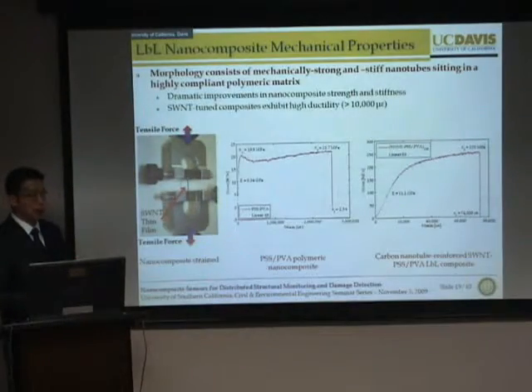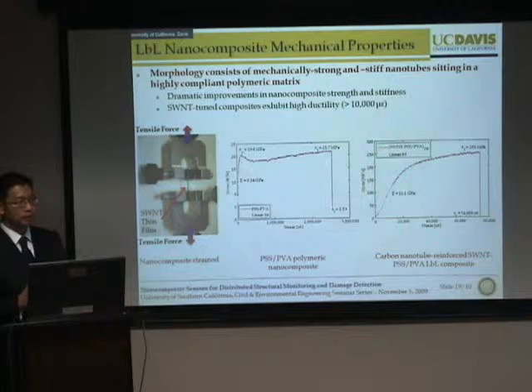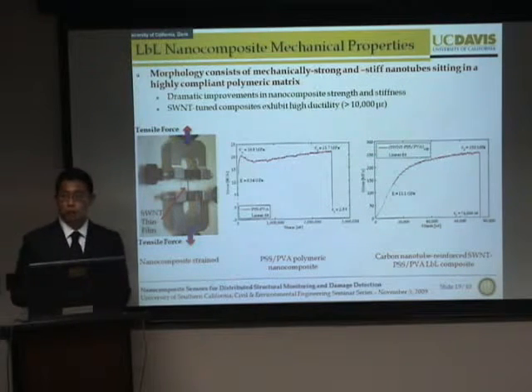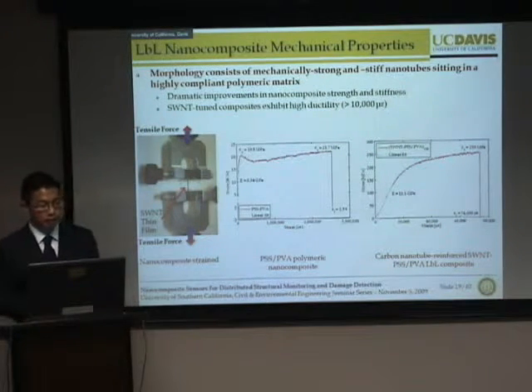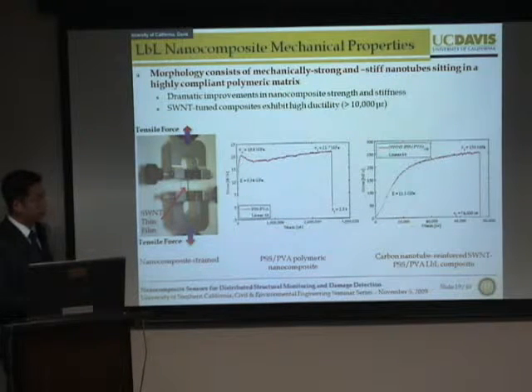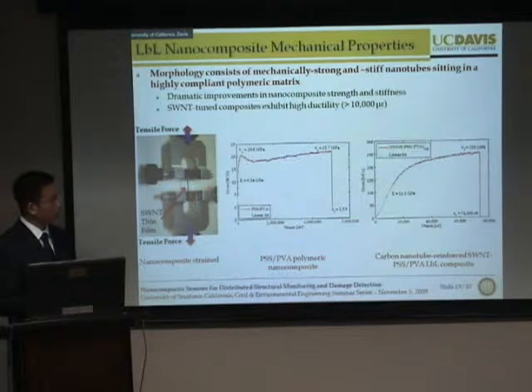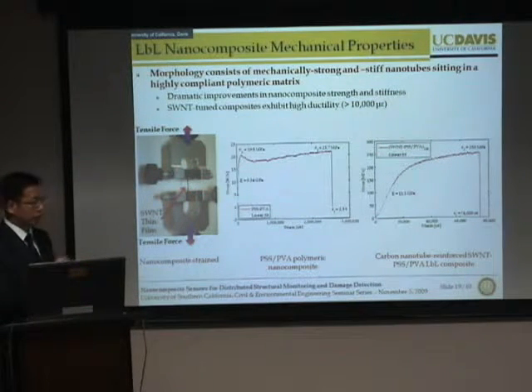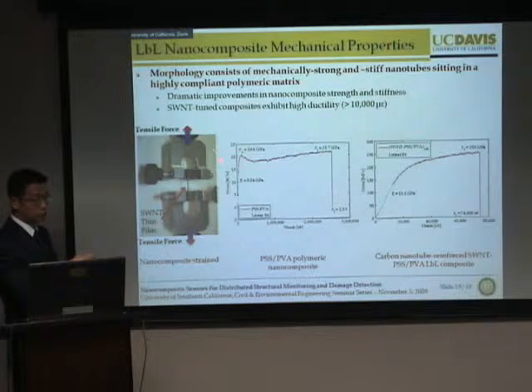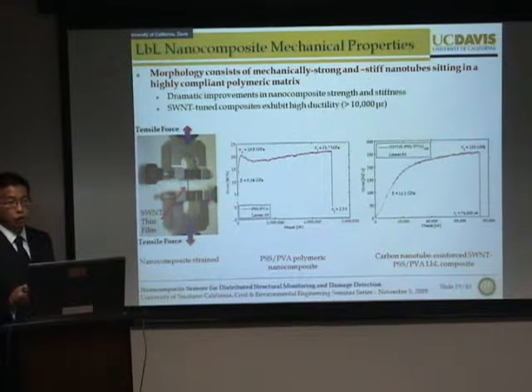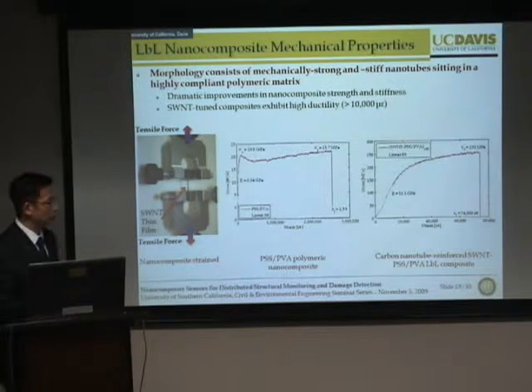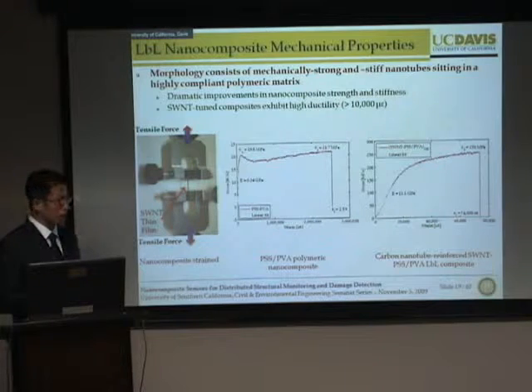Now, in order to create a true multifunctional material where we can combine sensing, the material should also possess impressive mechanical properties. So upon thin film fabrication, we wanted to explore how these materials perform mechanically. So again, upon etching the film to create a freestanding thin film, we can then mount it in a Test Resources 150R electromechanical load frame to investigate its stress strain performance. Now, before I talk about the carbon nanotube thin film behavior, we can first take a look at just a pristine PSS-PVA polymeric thin film stress strain response.